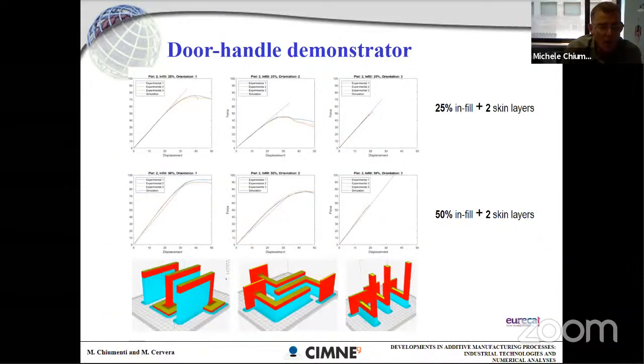Well, this is the result once terminated the sensitivity analysis. We did the work using 25% infill and 2 skin layers, and the second kind of specimen was built using 50% infill and also 2 skin layers. In the paper, you can find other combinations. But at the end of the day, the result is that the model is able to predict the stiffness of this material in all the different orientations.